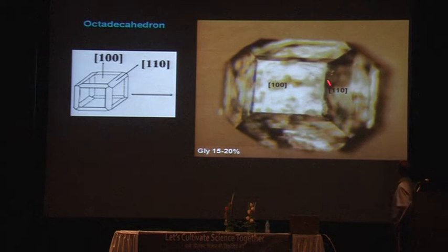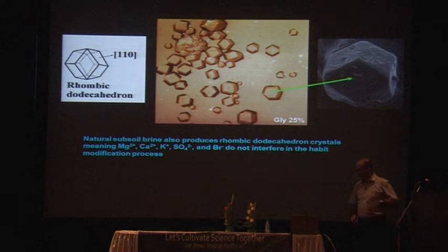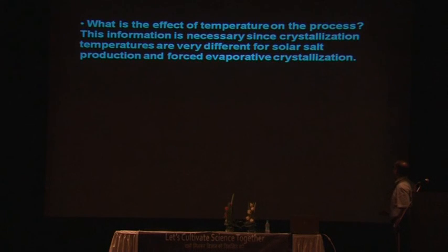This is a sodium chloride crystal. You can see that all edges are seen. This is 100 plane and this is 110 plane. So this plane is growing slower, this is growing faster, so it disappears, it retains, and as a result at the end you get rhombic dodecahedron. So these are the examples. You can see very nice crystal of sodium chloride. This is a scanning electron microscopy of the rhombic dodecahedron crystal. You can see very easily this rhombic crystal here.